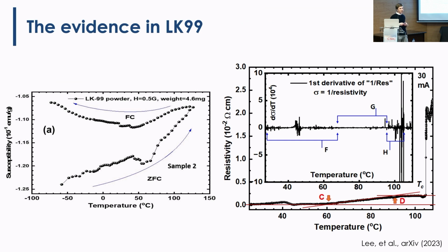Okay, good. What was the data that this paper put? They saw in the magnetic susceptibility a drop, signatures of a kind of diamagnetism, somehow of the Meissner effect. You see here, right? When they were cooling without magnetic field and when they were cooling with magnetic field, they saw that somehow there was a drop when cooling without magnetic field. And then this transition coincided, around 100 centigrade, it's very funny.